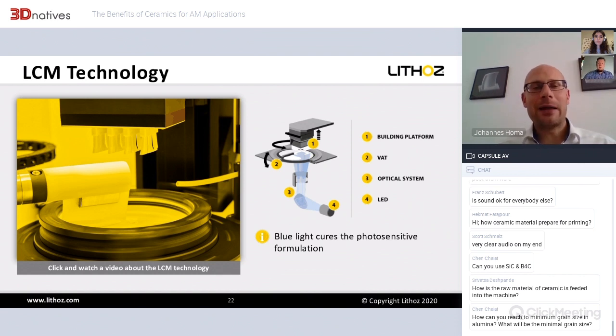But this setup, I think, is a very good approach on the one hand to achieve very accurate parts, because we can really control the layer thickness, and on the other hand, and this is especially true for ceramic materials, it is industrial ready. We need very little material to start with, and we do not have to have the full vat with resin, because what's the problem with ceramics? In the long term, you have settlement issues with particles, and if you have a big vat and settling issues, that's really a big problem for ceramic processing. But by doing this approach, we have this settlement issue under control, and we have very little material we have to keep as an inventory.